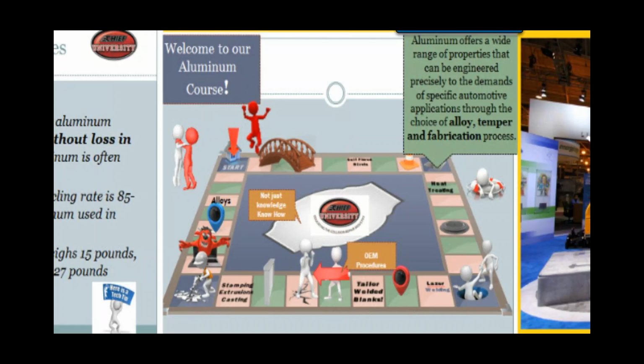It's very, very critical. You know, we have a full day class on aluminum, so it's hard to condense it all into this, but things like self-piercing rivet and bonding. A self-piercing rivet with the proper adhesive is 5 times stronger than a spot weld, 5 times stronger than a MIG weld. And the problem with a MIG weld is too many variables, right? It's too early in the morning, I had too much coffee, I got the wrong angle, I'm too far, I'm too close. Too many variables to determine a consistent weld.